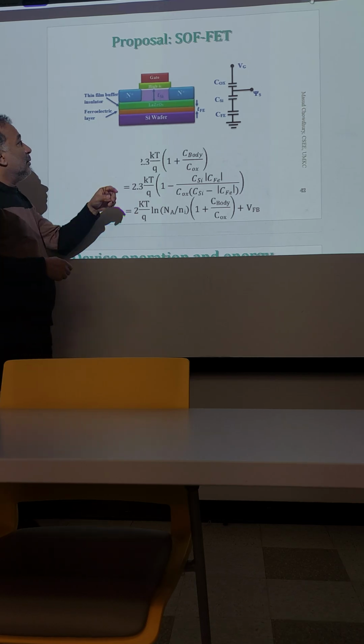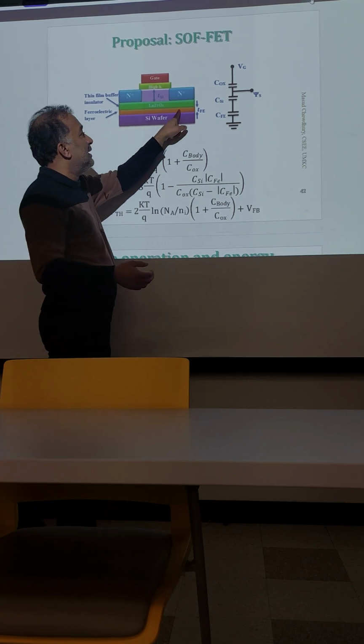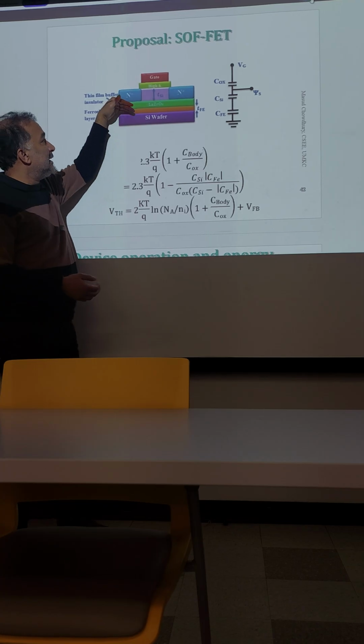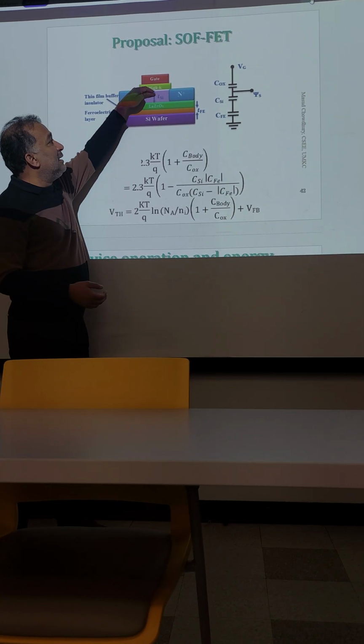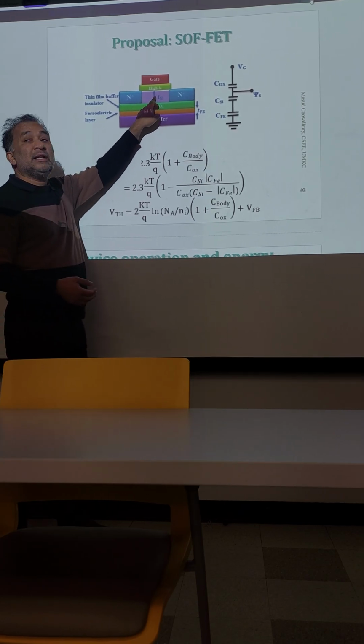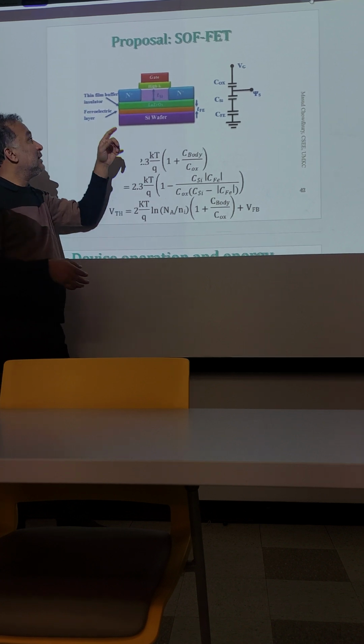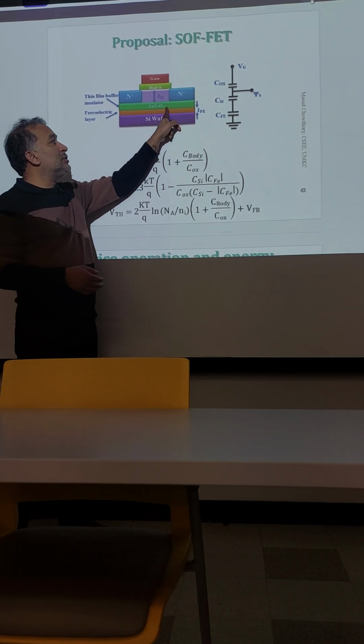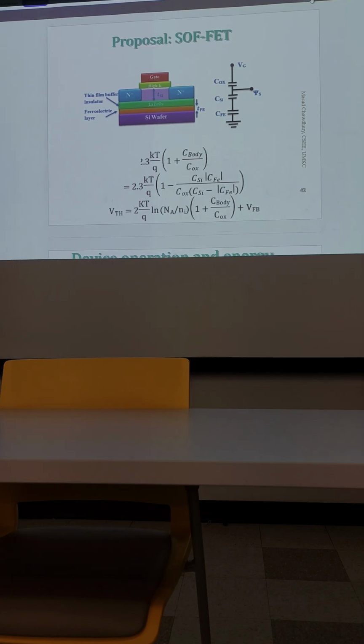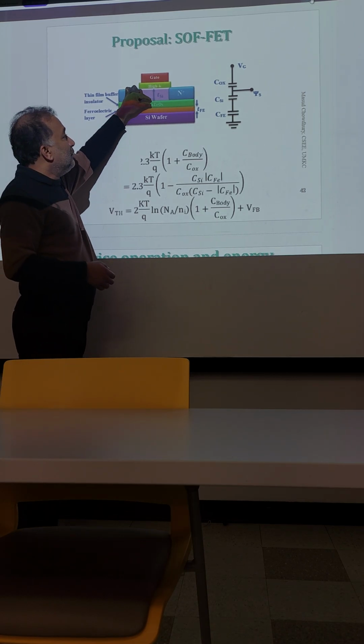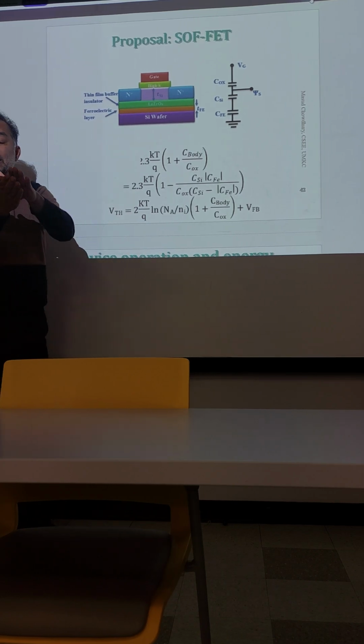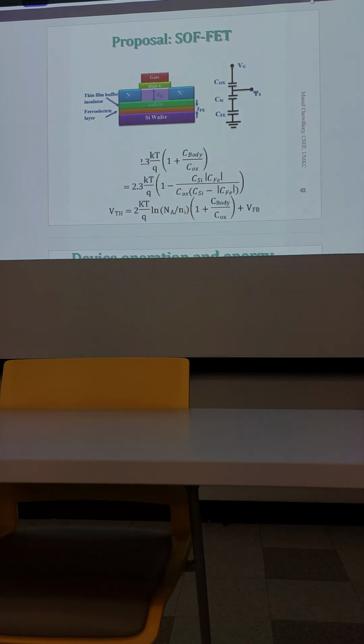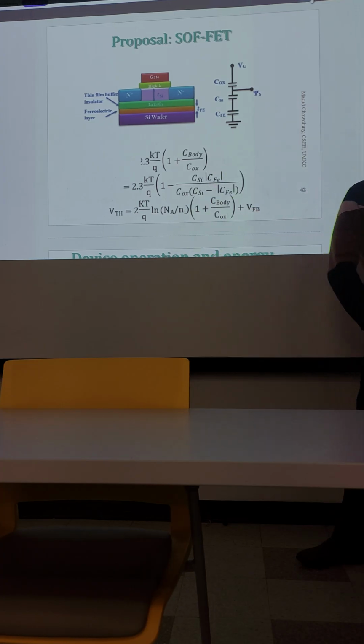So that will create a stability and reliability problem for the device. So the solution is, well, now the same question arises. If we put the insulation layer, like in an SOI device, a ferroelectric insulation layer inside the body, then from the bottom surface of the channel, this ferroelectric insulation will react with the silicon channel and change the silicon property. So the solution is, let us put between the channel and the insulation layer a neutral layer of thin buffer material, which will not react with silicon. So silicon will be protected. We could put this buffer layer in the gate as well, but then gate thickness will increase. If gate thickness increases, device drive will become slower. Then you need higher voltage to turn on the device, because the goal is to make the gate insulation as thin as possible, right?